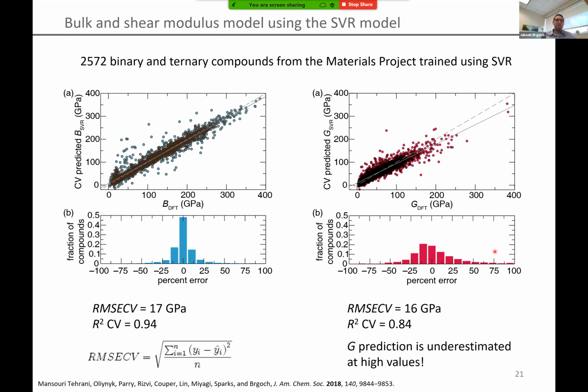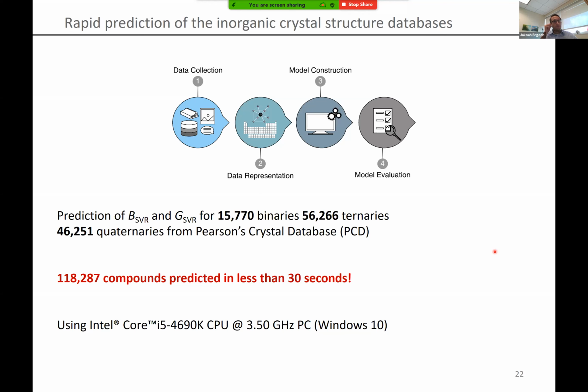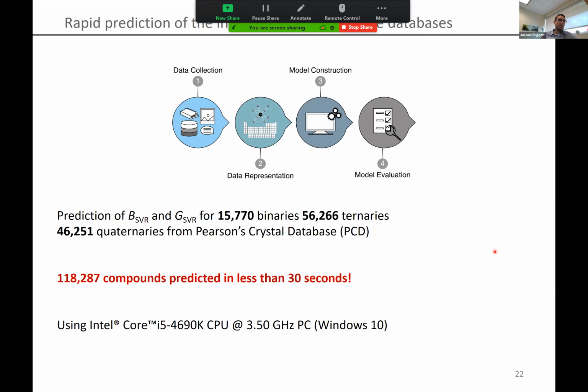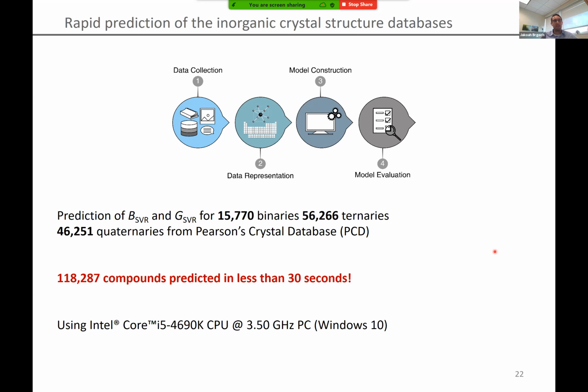So what we did was go back to the Pearson's Crystal Data set and extract 118,000 compounds, including 15,000 binaries, 56,000 ternaries, and 46,000 quaternaries. Once you train the model, which doesn't take all that long because support vector machine is really efficient even in terms of training, we're able to predict both bulk and shear modulus in less than 30 seconds for more than 118,000 compounds — and we're not using any high performance computing clusters here, just a normal desktop. So this is pretty impressive: to take the 2,572 input data and scale this really reliably out to 118,000 compounds.